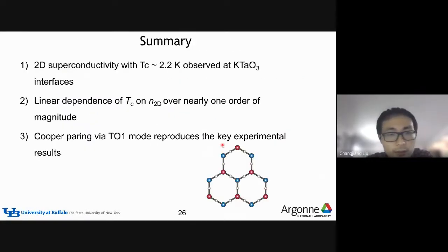So with that, I'd like to summarize my first part. I explained that we found for the KTO-111 surface, we can achieve a superconductivity with the TC as high as 2.2 Kelvin, while we further found that the TC is highly dependent on the crystalline orientation, with TC being linearly dependent on the carrier density for the KTO-111 surface. So we found that the pairing via TO1 phonon could reproduce the key experimental results. So this concludes my first part. Let me know if you have any questions.